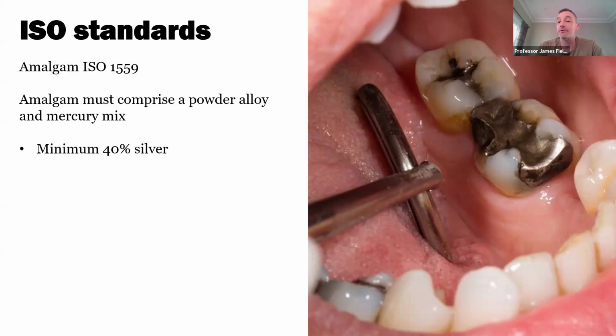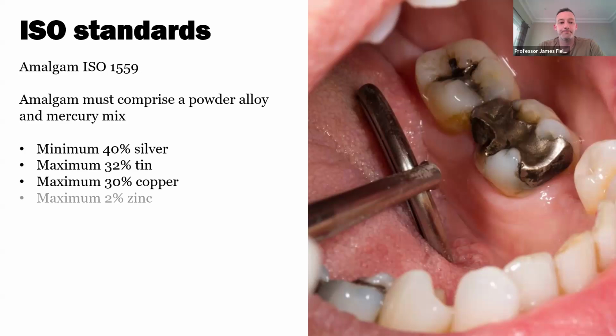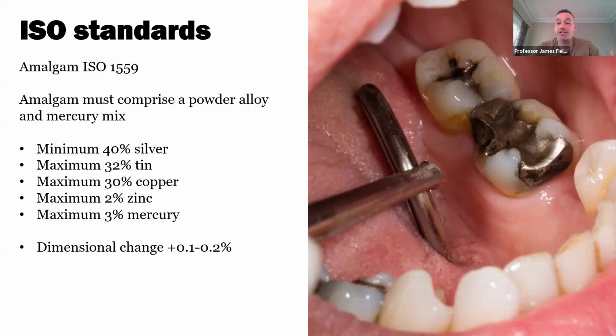The alloy had to be a minimum of 40% silver, which often surprises people. And it had to be a maximum of just under a third tin and a maximum of just under a third copper. And it also had some other things in there to scavenge free radicals and also to prevent creep corrosion. But interestingly, it had a maximum of 3% mercury. When you talk to people and patients and actually other oral health professionals, there's a misconception that dental amalgam had a huge amount of mercury in it.